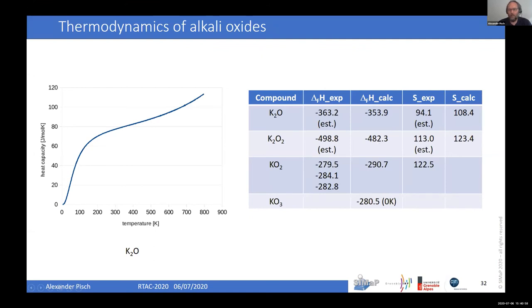But the entropy derived from the low temperature heat capacity measurements is really completely different. So they're much higher in both cases, which may in the end give you the same Gibbs energy, at least at room temperature, because both balance a little bit. But when it goes then to higher temperature, it may give different values. So now these values can be used to make a full CALPHAD assessment to see how this behaves in the multi-component system.